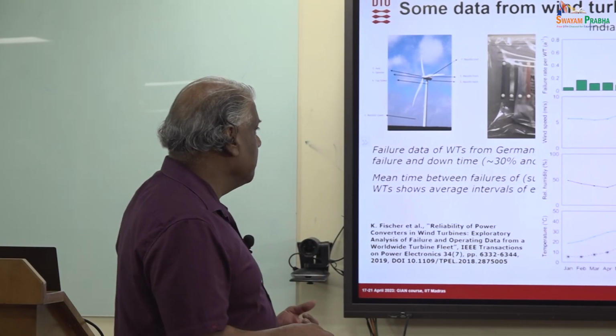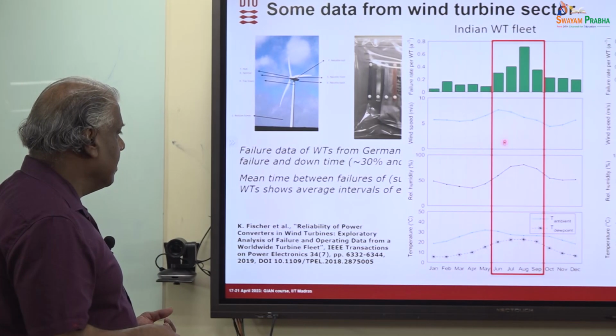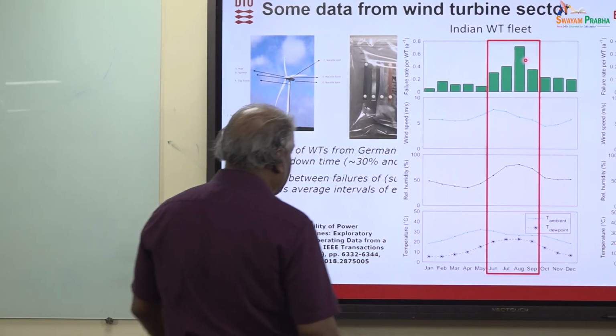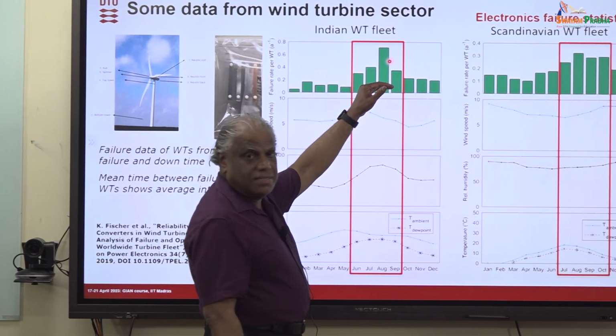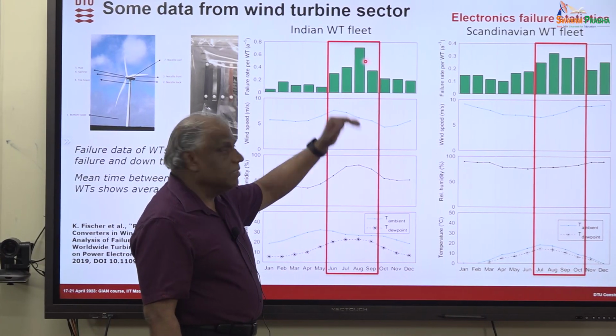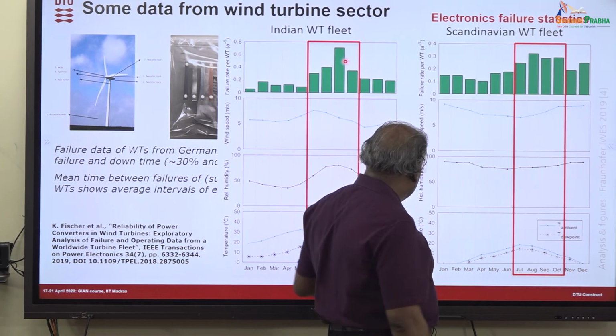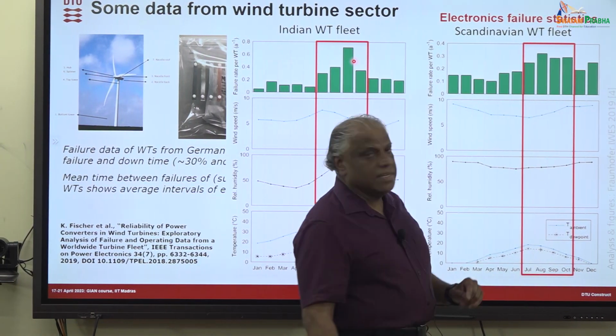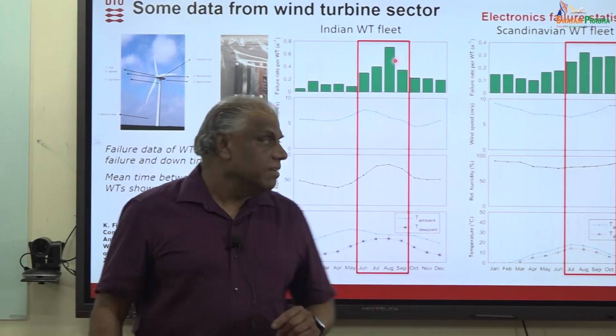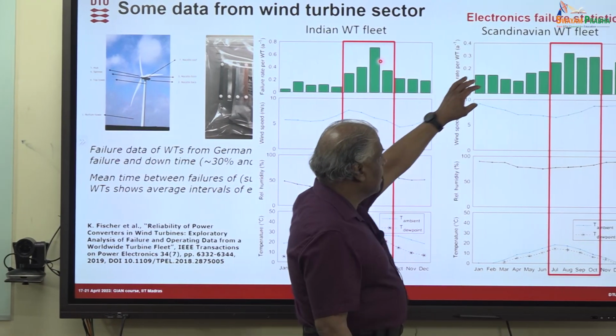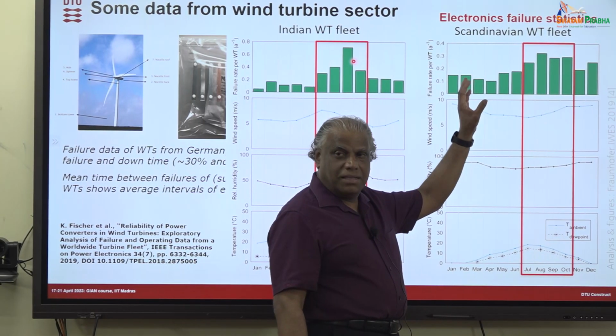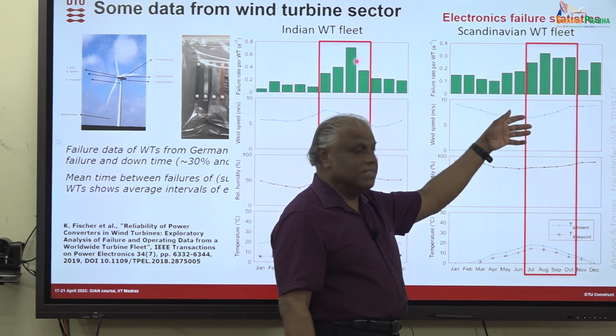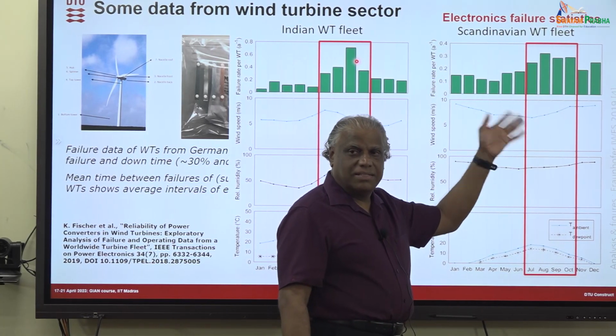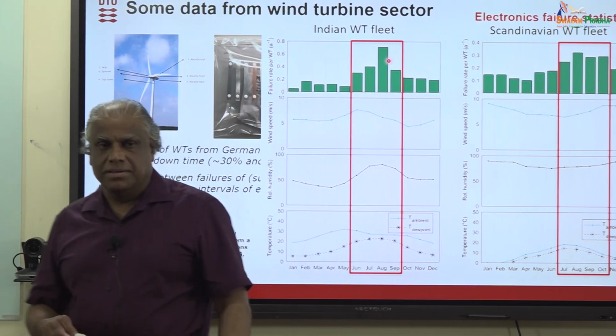That doesn't automatically mean it is due to corrosion, but they did the analysis. They collected all these failures and analyzed them, and you can clearly see that many of them are due to corrosion failure. So there's a clear indication that the climatic conditions, and how they are changing, are leading to more electronic failure due to corrosion. You can see a similar effect, slightly shifted by a month, in the Scandinavian fleet as well, with more failures there too. That's because in Scandinavia the temperature is always lower, and in winter you can have a lot of condensation and things like that. So that's the reason there are failures all the time.